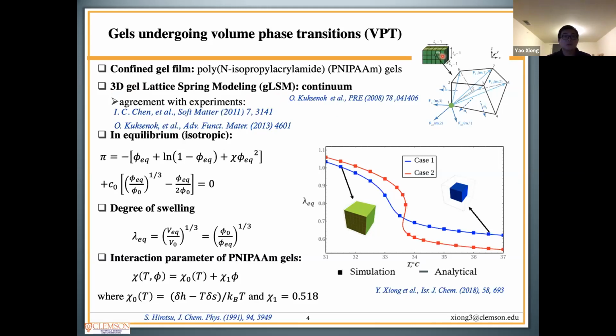Upon equilibrium after isotropic swelling or shrinking, we can solve this equation to get the equilibrium volume fraction of polymer in each element, where chi is the polymer-solvent interaction parameter, C0 here is the dimensionless cross-link density, and phi0 here is the volume fraction of polymer at preparation. Once getting the value of phi equilibrium, we can use the degree of swelling to estimate the relative change in the gel due to volume phase transition.